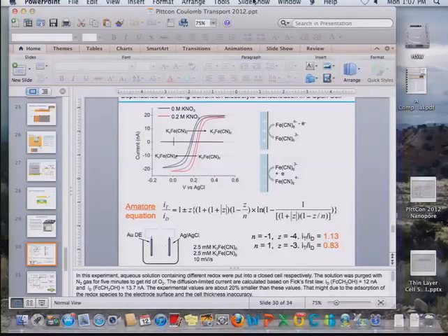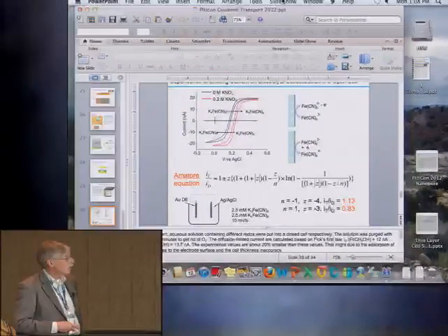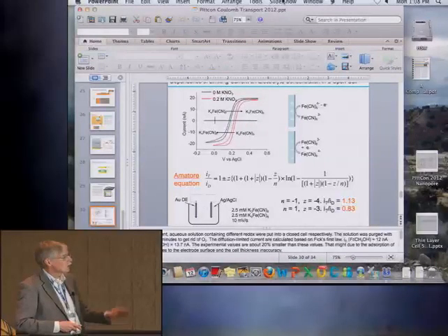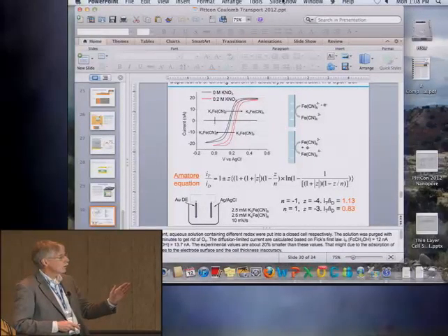Now you go to a charged reactant, ferrocyanide, and this experiment is just at a gold disc electrode using a real reference electrode. So we're just measuring the oxidation of ferrocyanide and the reduction of ferrocyanide. This is in 0.2 molar electrolyte, potassium nitrate, and then you take the electrolyte out, and you see the curve. There's a shift in the potential.